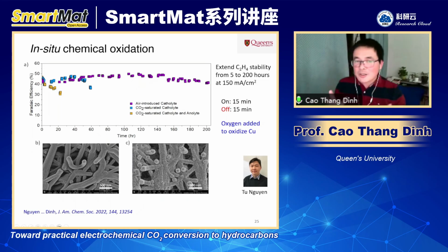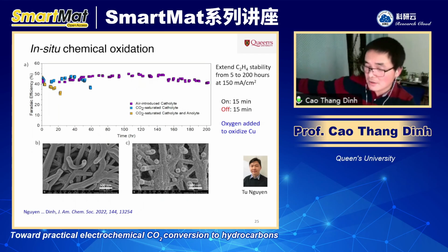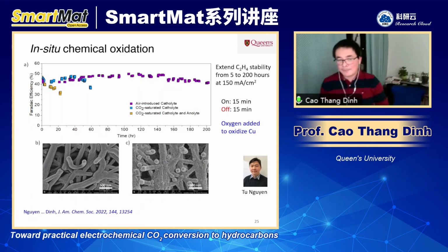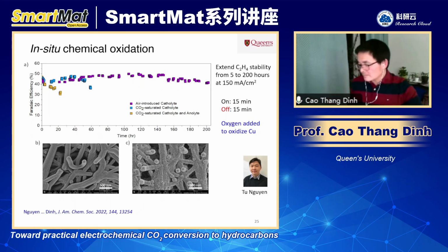So this is only on time, right? We did not count the off time there. So that means we run the reaction for 400 hours in total, and 200 hours is on time. And we check the surface after the reaction, and we see the micro scale is changed, but in general, you still have some copper, the same morphology of the copper.